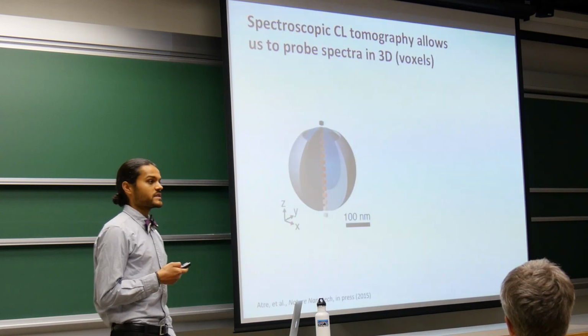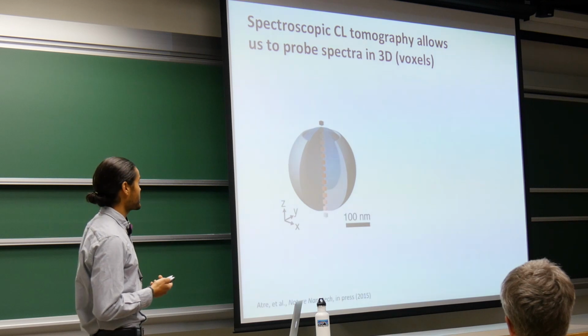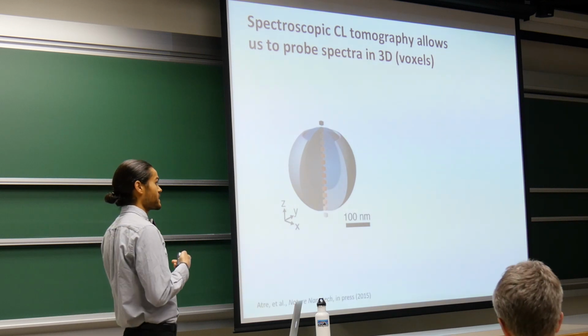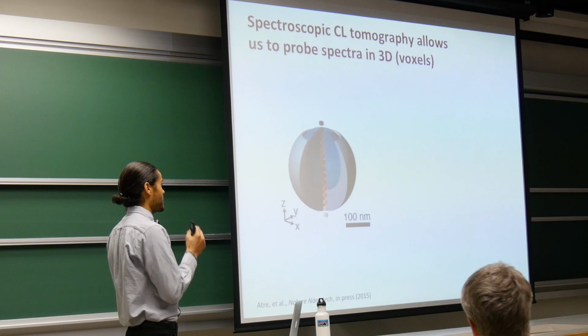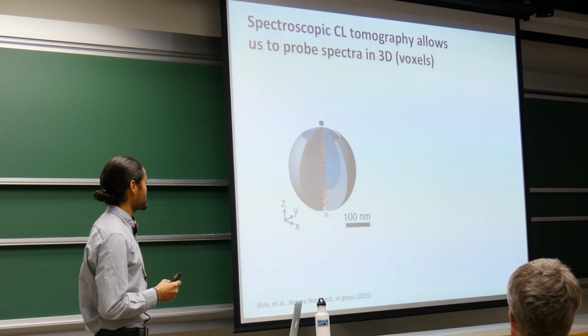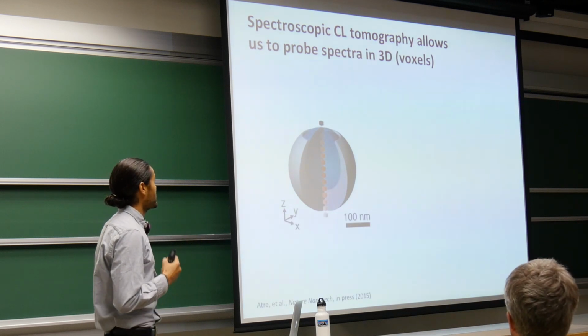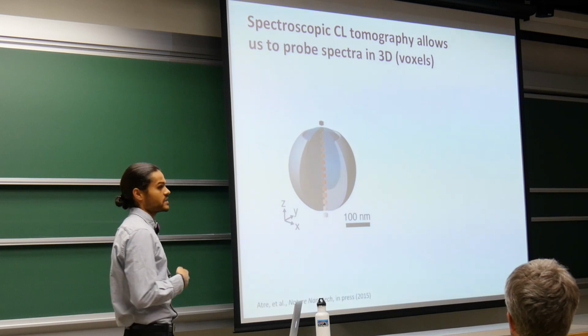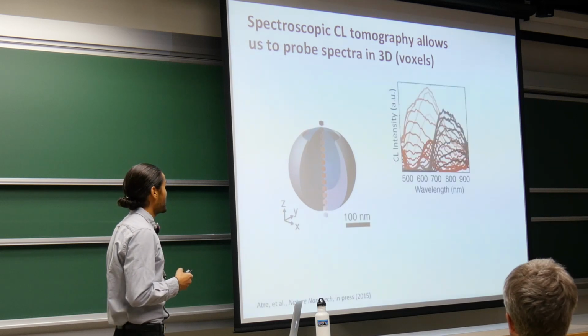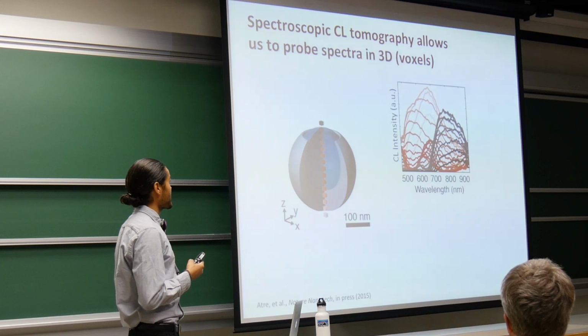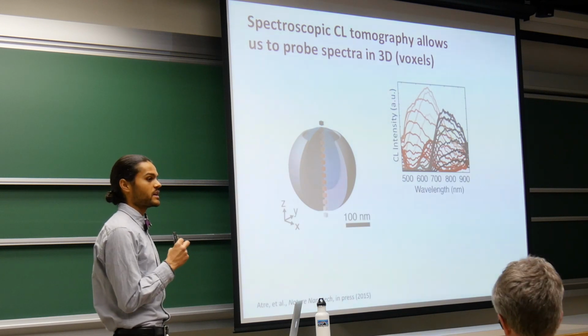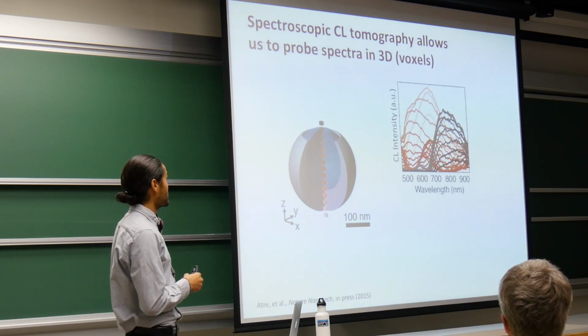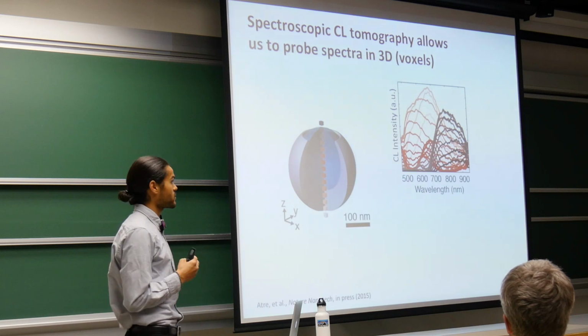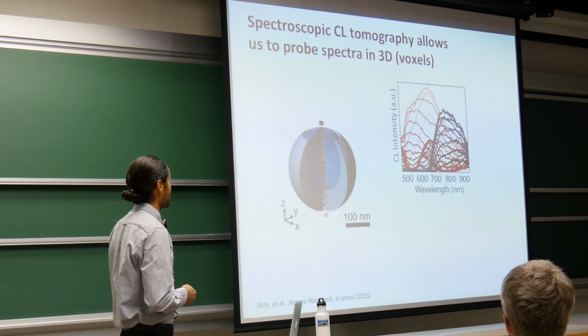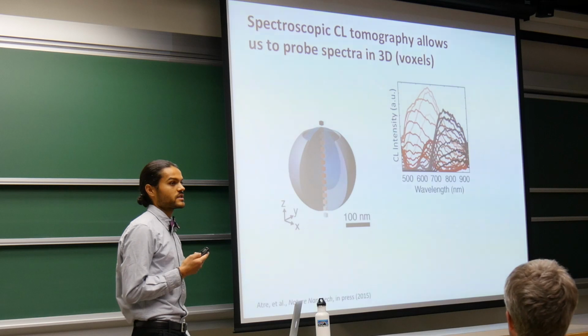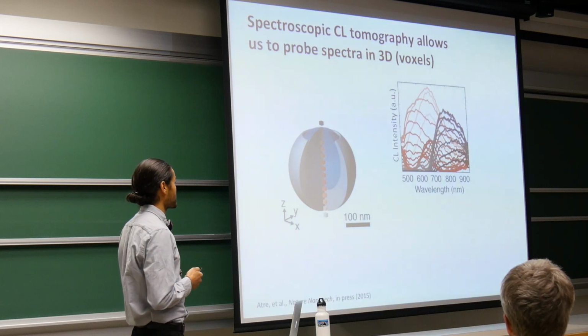Of course, cathodoluminescence, as I've mentioned, is a spectroscopic technique, so we can probe the cathodoluminescence signal at every point in our 3-dimensional space of our reconstructed tomogram and plot out spectra for each of these voxels, or 3-dimensional pixels. And when we do that, we can see, as we expect, when the voxels are located in the base of this crescent structure, the signal peaks at shorter wavelengths corresponding to the material luminescence, and then for voxels closer to the tips, we see the strong plasmonic resonance.